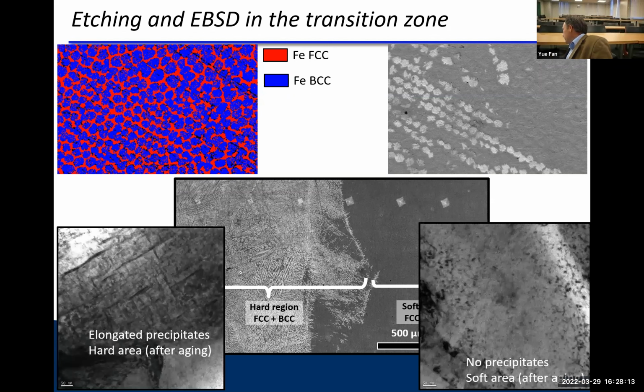In the TEM, however, we did see that in the hard region, we see a lot of intermetallic precipitates, but not so much here. So what seems to have happened is that in the hard region, we form a lot of intermetallic precipitates that use up some of the alloying elements, therefore it doesn't contribute to the corrosion resistance and that allows it to etch, versus in the soft region, we do not form those intermetallics, and therefore it also doesn't etch because it stays in solution. So that's one example where, when you set off to do a gradient, you have to be really careful that the gradient is indeed a gradient and not a sudden transition in some way. That's something to keep in mind when you do this grading.